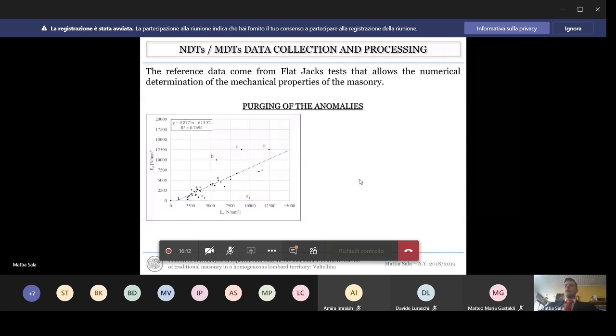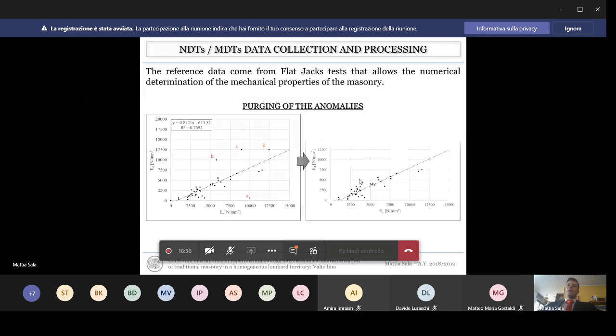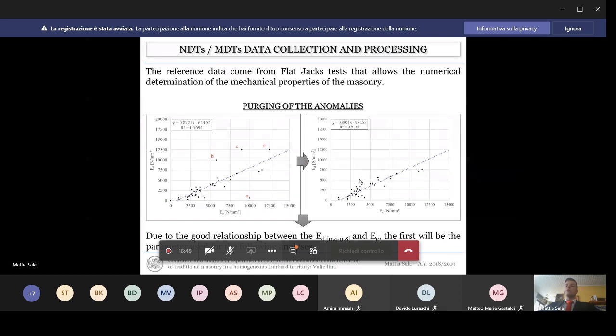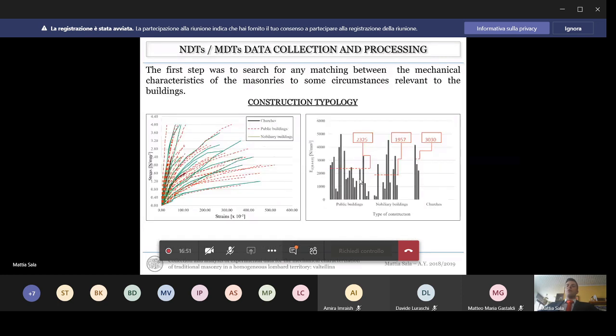According to the Italian code, among the tests done, the flat-jacks are the only ones suitable to directly determine the characteristics of the masonries. By correlating the deformability modules calculated on the first loading step and the elastic module on the unloading step, we see that there is a good linear correlation, apart from some data highlighted with a letter. Considering these as anomalies and removing them from the data set, we arrive at a better value, with an R-square of 92%. And for this reason, the deformability modules are the ones used for the following analysis. So the next step was to search for some matching between the mechanical properties of the masonries and some circumstances which could be relevant for the buildings.